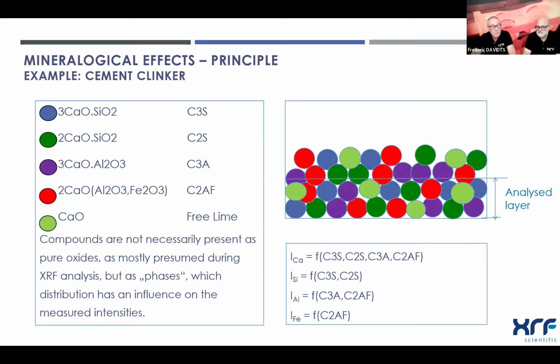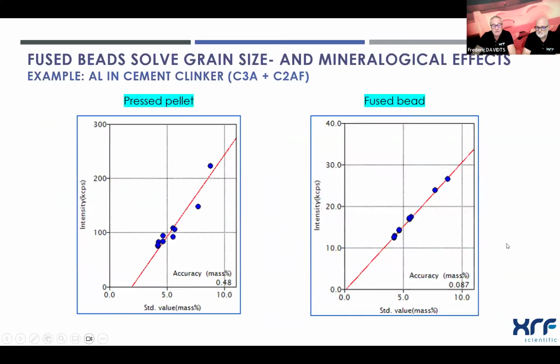As an example, we have here the cement clinker, which, if you look closely at calcium, has 5 different phases. So the calcium really comes from 5 different phases, and therefore also the intensity is from those 5 different phases. So the compounds are not necessarily present as pure oxides, but as different kinds of phases, also called structures, which again have an influence on our intensities. And we can see here an example.